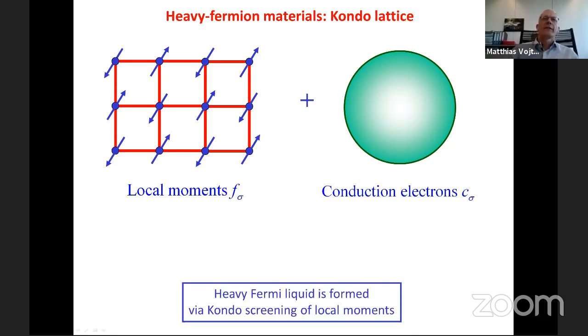And one thing which often happens in these materials is that the conduction electrons screen these local moments by a lattice version of the famous Kondo effect. And then one ends up with a paramagnetic metal where essentially these local moments have been eaten up. This is then called a heavy Fermi liquid. And this is one of the possible phases.